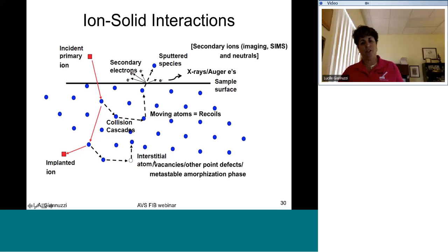So it can result in interstitial atoms or vacancies or other point defects. At the extreme, it will also cause a metastable amorphous phase, and we'll talk more about that later. The other thing that you will also get at the surface are the generation of the secondary electrons. These are caused directly by the incoming incident primary ion as well as the energy of the moving recoils. You'll get sputtered species. You can also get X-rays or Auger electrons, but these signals are very, very low.